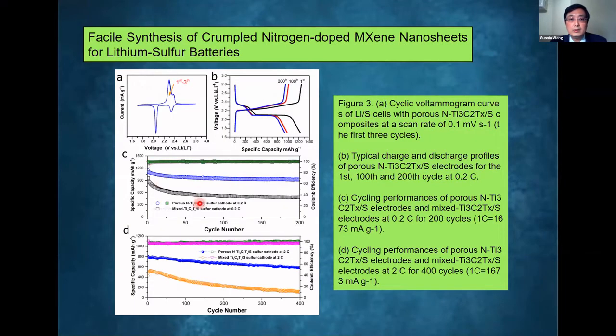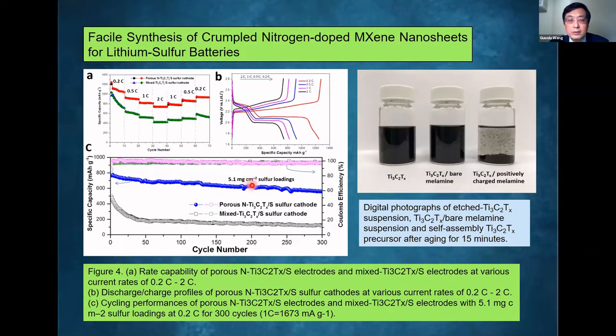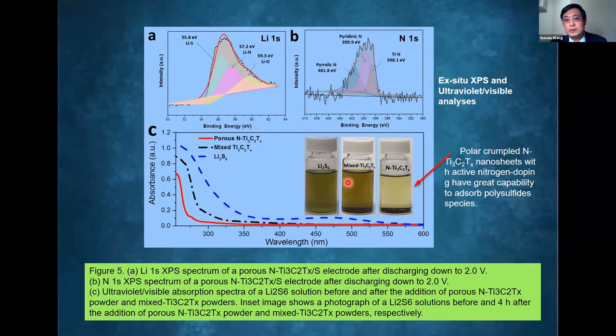You can see when we use the porous nitrogen-doped MXene sulfur cathode, we achieve better electrochemical performance than the stacked MXene cathode. And also we did a high sulfur loading. In this case, it's a 5.1 milligram per square centimeter sulfur loading, which is very high, considered in the field of lithium sulfur batteries. And also we achieved a very good cycling performance. And also we further did the absorption observation. You can see the nitrogen-doped MXene can show strong absorption towards lithium polysulfide. That explains why the nitrogen-doped MXene cathode can achieve better electrochemical performance.